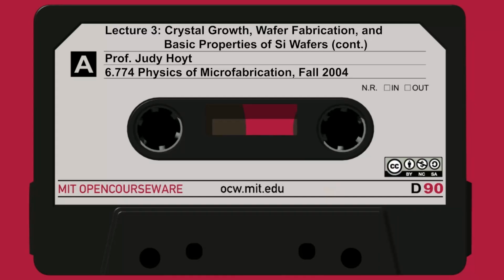That's the pure interstitial. Some people, the defect experts, also refer to a type of interstitial defect called an interstitialcy, sort of by analogy to a vacancy. It's an extra atom, but actually 2 atoms that are sharing a lattice site. So these 2 are together, and there is some bonding to neighbors, as opposed to a pure interstitial. A lot of people believe that the interstitialcy is actually the most likely configuration of the interstitial defect in silicon, because it takes lower energy to create it. Just sharing a lattice site isn't that hard compared to stuffing an unbonded atom in there. But the truth is, the distinction is really not important in process modeling.